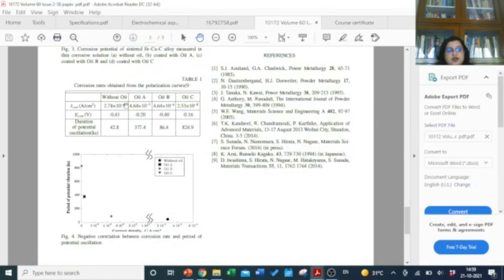Instead of that, when researchers do these kinds of tests, they can quantify these in terms of MPY, MMPY, and they can do the EIS as well for the salt spray test. When they do the salt spray, they can do it before and after 48 hours. So, they can see the difference in the reduction of EIS.